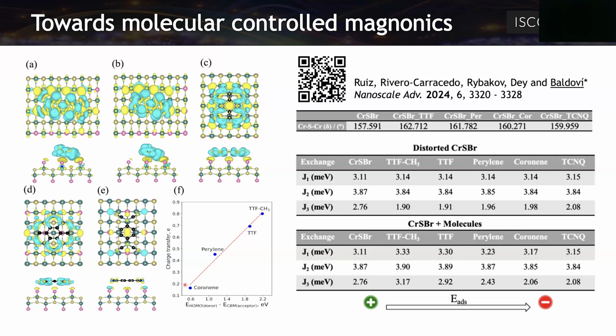Then we take the donors that are the important ones, and we can see this nice correlation. So we are adding here the charge transfer that we got from the initial calculation, that are these blue dots, and we can observe that we are going from TTF to TTF-CH3, but we also did a very fast calculation of getting the highest occupied molecular orbital, the energy of the HOMO, of the donor molecules separately, just a point by point calculation of these molecules, and then the conduction band minimum of the acceptor.